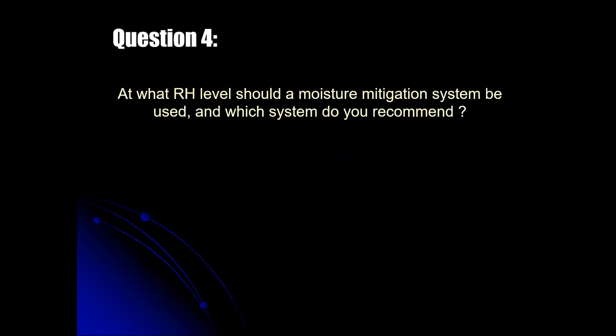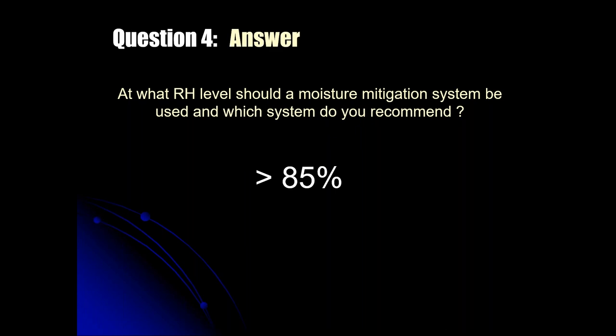Question four, at what relative humidity level should a moisture mitigation system be used and which system do you recommend? I'm very conservative. And the reason I say 85% is because I'm one who believes that liquid moisture can develop in the pore structure and capillary structure of concrete at less than 100% relative humidity. The capillaries in concrete are thought to measure in the millionths of an inch in diameter. So not something you can even see readily. So a lot of it's theoretical.